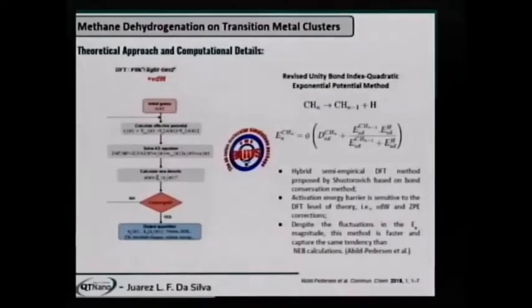And I want to highlight that these activation energy barriers are sensitive to the DFT approach. So you can have the trends, but you may not have the right value, since you have to use van der Waals corrections and also ZPE corrections in the adsorption energy. They directly depend on how you obtain that adsorption energy. So despite these fluctuations of this method, you can compare with other methodologies available, like NEB.